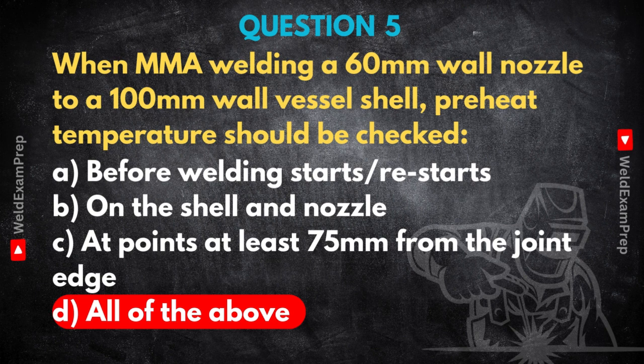And third, checking at points at least 75 millimeters from the joint edge. Why that distance? Because it ensures you're measuring the bulk material temperature, the heat soak, not just a superficial surface heat that might dissipate quickly. That 75 millimeters gives you confidence you've heated a sufficient volume of material around the joint to the required temperature. That's what's needed to slow the cooling rate effectively and prevent problems like hydrogen cracking or excessive hardness. So it's about heating a significant zone, not just the immediate edge.